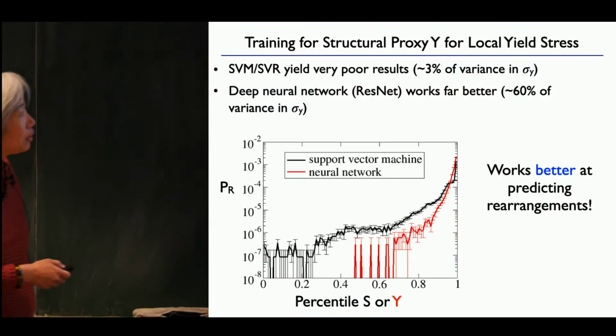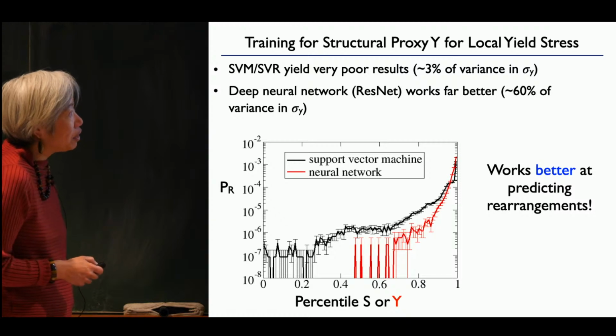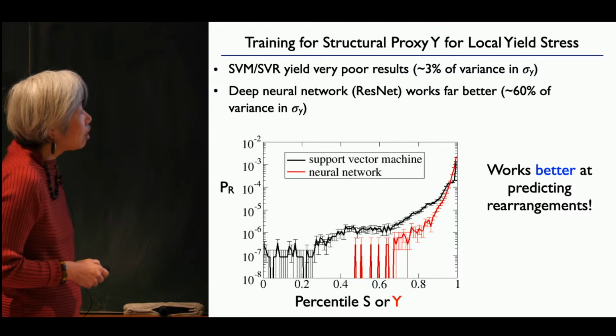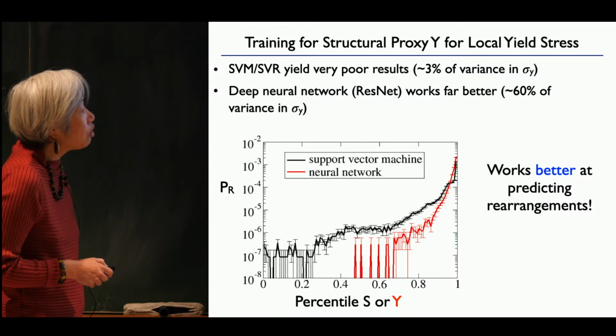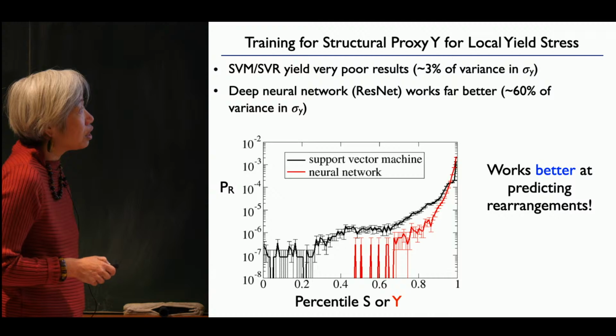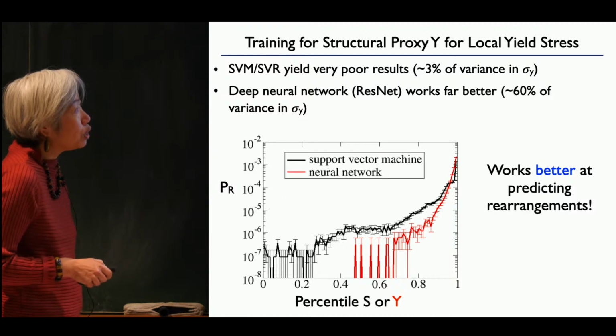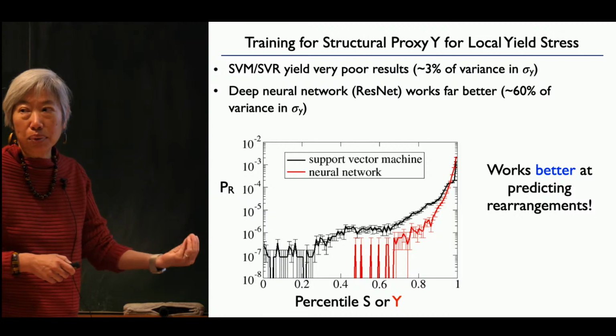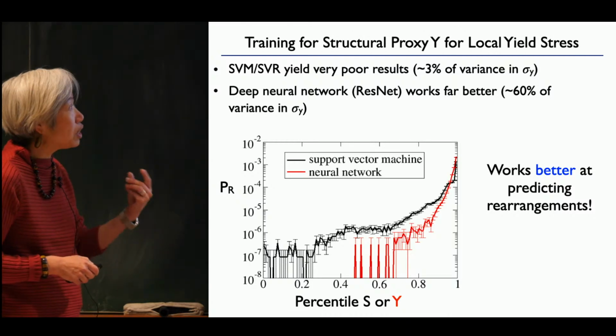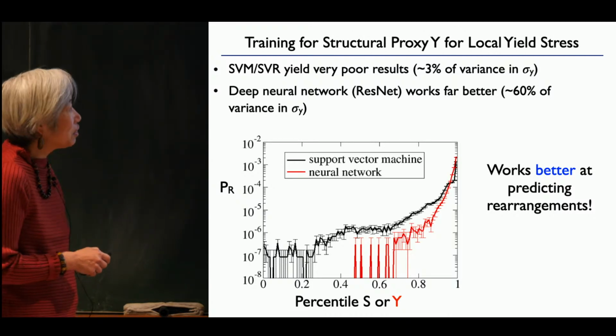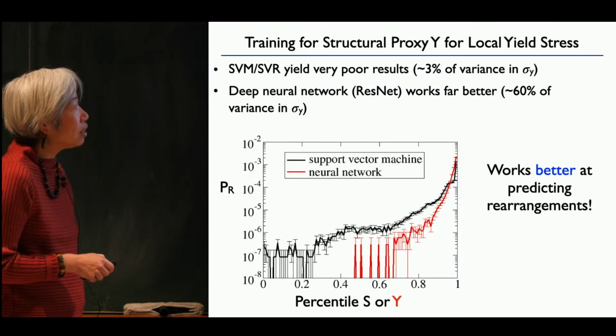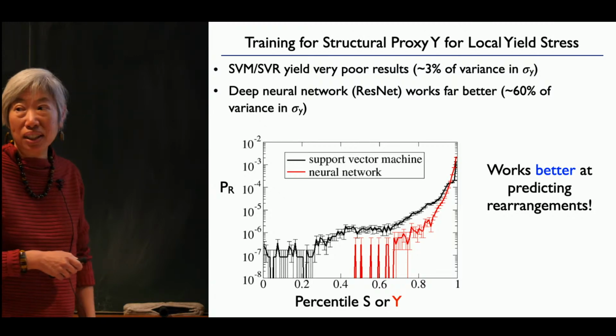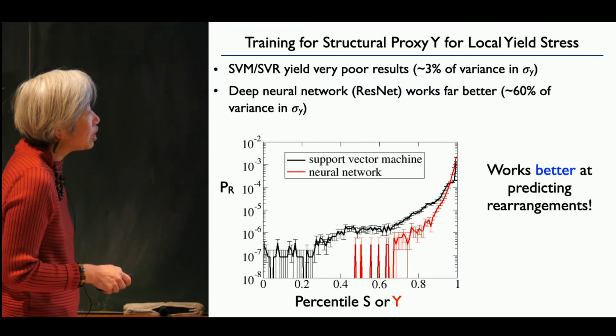And you see what comes out. So this is the probability of rearranging. This is on a log scale, so you see it covers several orders of magnitude. So it's a reasonably strong function of softness. It's not terrible. But it turns out that predicting local yield stress, a structural predictor of local yield stress, is a better predictor of rearrangements than training on rearrangements themselves using a support vector machine.